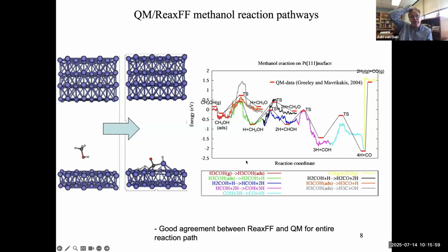Also, we can look at competing reactions. A very important competing reaction for methanol dissociation on platinum is here, the gray curve. Breaking the CO bond is very, very high energy on platinum. And so indeed, we know that platinum in fuel cells suffers from carbon monoxide poisoning, because there's really no way out. You go all the way down to harvesting all the hydrogens, you end up with carbon monoxide, and carbon monoxide pretty much occupies your surface.